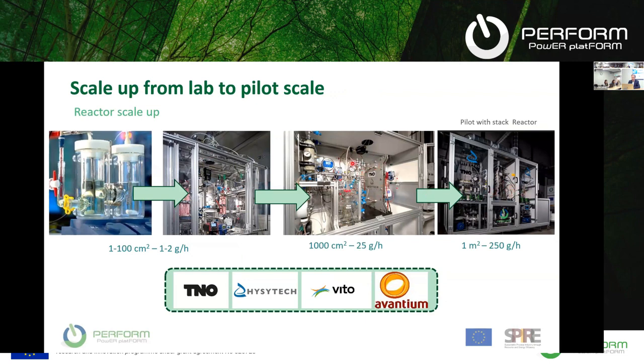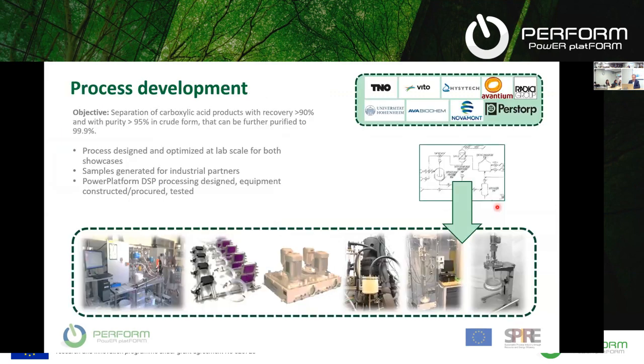So this is a 1,000 square centimeter reactor that was built by Hysytech, and also this pilot here, the 1 square meter stack reactor in the middle, which you can see downstairs later today if you're here. It was built by Hysytech and designed by TNO, Hysytech, and VITO. So this is how we worked over the years, and you see that you are going from very low TRL levels for new electrode materials to a TRL 5-6 pilot, with increased surface area and increased productivity.